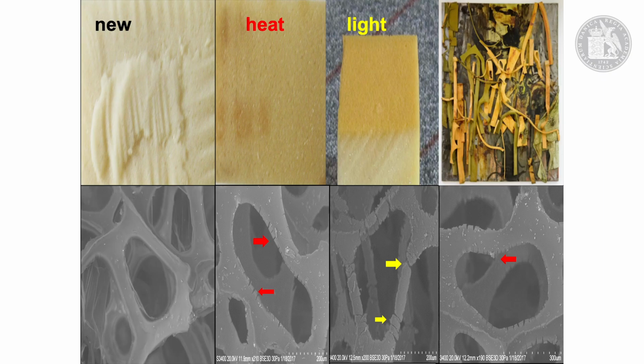So we did some accelerated aging to see if we could make some copies of that degraded foam. We have some new foam on the left, some heat aged foam. We use 60 or 70 degrees centigrade because that's what you use if you do medical testing on plastic materials, and expose them to sunlight. And we were allowed to take small samples from the artwork as well.